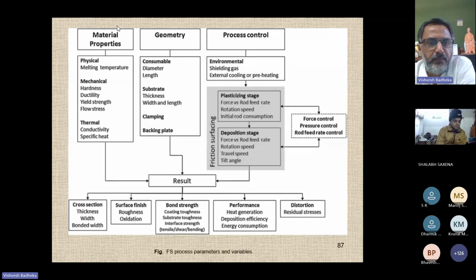If you see the process parameters, material property is one parameter: what material you are taking, the rod material, the rod diameter, base plate material, base plate dimensions. Similarly, the geometry: rod diameter, rod length, thickness of substrate, the clamping, the backing plate. Then the process parameters: whether you are working with external gas, environment, external cooling, external preheating. And finally, whether your system is a force-based system or a feed control system. This is also another important parameter.